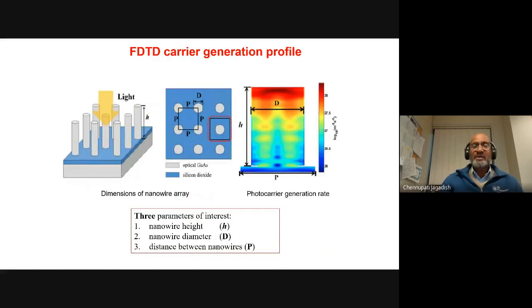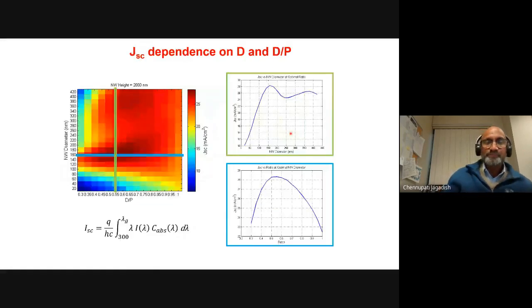Again, we've done lots of simulations, and Dr. Sudha Makapati, who is now an associate professor at Monash University, is involved in this particular work. She is working with students, and we're able to look at what should be the diameter of the nanowire, the distance between the nanowires or the pitch, and also the height of the nanowires and various things. As you can see, most of the current is generated at the tip of the nanowire, indicating that you don't need very long nanowires. These gallium arsenide or indium phosphide 1 or 2 micron long nanowires are more than sufficient to collect most of the current, for example.